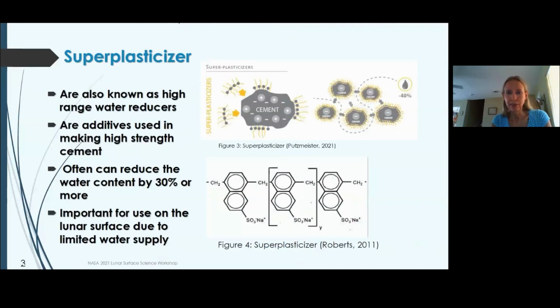And what we are interested in is using regolith-based cements and finding a good superplasticizer for it. Superplasticizers are also known as high-range water reducers. Basically, if you have cement, you can put a superplasticizer in it, and then you don't have to add as much water to get the same strength. And this is very important, obviously, for use on the lunar surface because you have a limited water supply there. Often it can reduce the amount of water you're going to need by 30% or more.